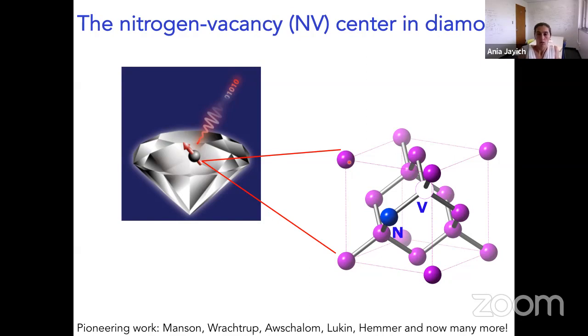Okay, so one might think it might be hard to control the quantum degrees of freedom of such a localized defect because of the presence of the lattice, but diamond actually makes a pretty good analogy to a vacuum. Why? In fact, for a solid state system, diamond is probably about as good as you can get. And why is that? Because it's stiff. That means it has a high Debye temperature of over 2000 Kelvin, which means that there's a very low population of phonons even at room temperature.